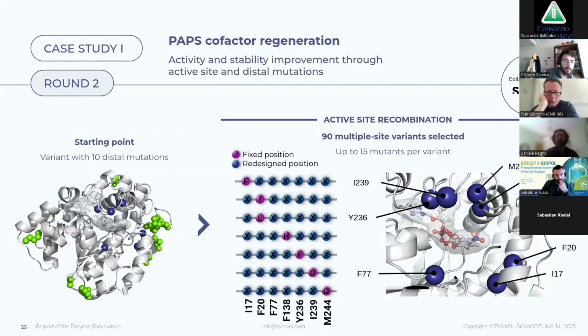So what we did was Sanofi internally selected this variant that already had 10 distal mutants, and then we did up to 5 more mutations at the level of the catalytic site to generate 90 recombinant proteins. Essentially, we had up to 10, or up to 15 with the 10 distal mutants, plus this other 5 at the level of the catalytic site.